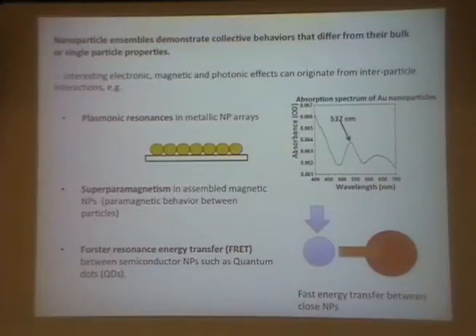This effect is actually used a lot with dyes in biology and fluorescence microscopy. If you have two complementary dyes of slightly different absorptions, you put them very close to each other, then one will transfer its energy to the other, and then will emit at a lower energy. So that effect is used all the time to detect if two molecules are very close to each other. Like, say, if you wanted to know if one molecule is binding to another, you can use FRET. But the same effect can be seen in quantum dots as well. We've been able to detect some of those effects.